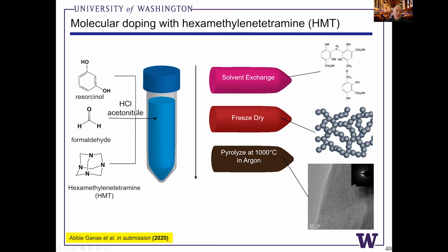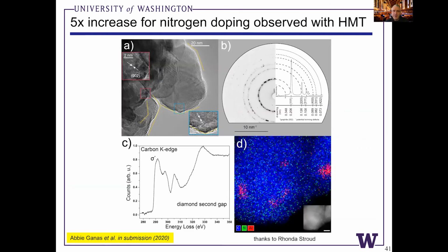identical. We add this molecule to our acetonitrile solvent with resorcinol and formaldehyde. We have to be careful also not to catalytically decompose the molecule. And if you're interested, I'm happy to share these results and show that we're not decomposing the HMT during gelation. We think the pyrolysis step is a problem for decomposition. But we were able to recover these materials after synthesis.